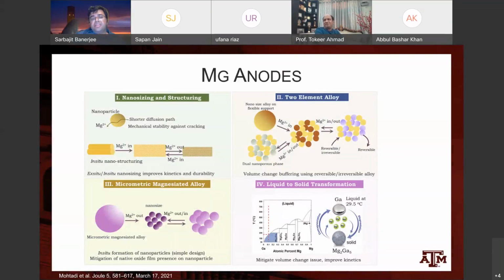And so on the magnesium anode side, nanosizing and structuring is part of this idea, using shorter diffusion paths, and that gives you some mechanical stability against cracking. Using two-element alloys is also pretty common, with bismuth, antimony, indium as examples, using micron-sized, in situ formation of nanoparticles of magnesium, and even liquid to solid transformation. And if you're using a liquid metal anode, that makes dendrite formation impossible, right? So this is one way to do this.